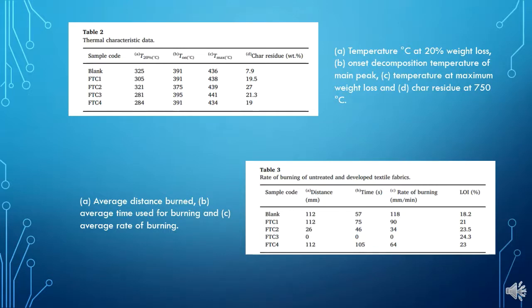As you can see on table number 3, the untreated textile fabric was burned with the recorded rate of burning of 118 mm per minute and the LOI of 18.2. However, when the coating layer was coated on textile, the rate of burning was reduced, achieving 90 mm per minute, which indicated a higher LOI value of 21.